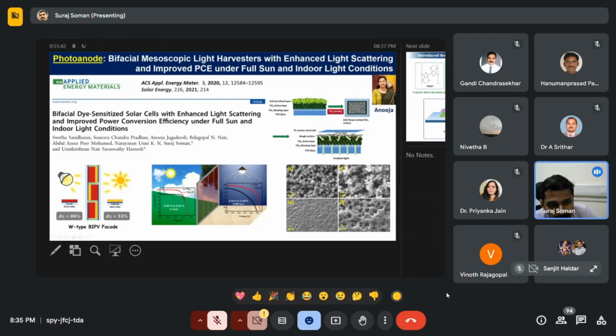So the advantage here is that you are completely avoiding your scattering layer, but at the same time you are creating certain grooves and impressions which act as the scattering center. Thereby you can improve the performance. For the front electrode, when you shine the light through the front portion, through the photoanode, there is around 84% improvement in the performance.